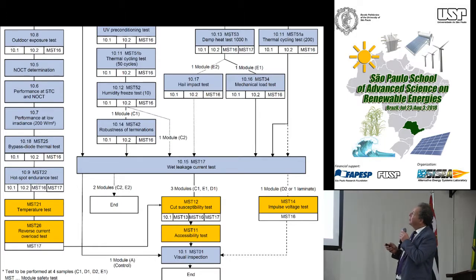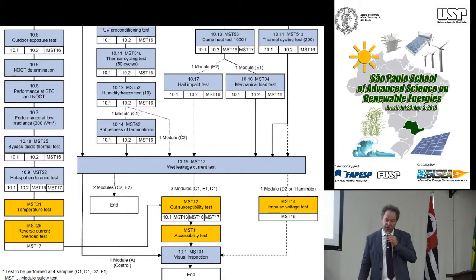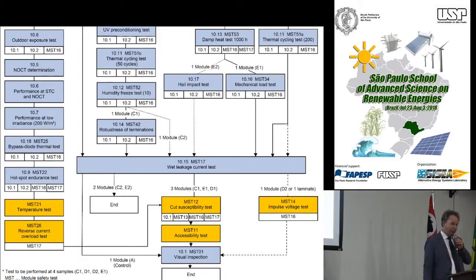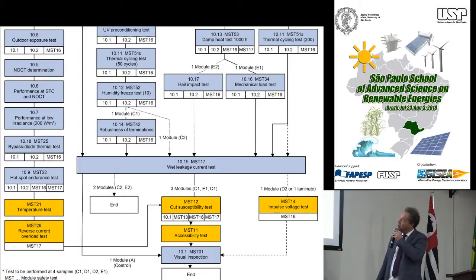Then again, we have the leakage test and the mechanical load test. This is equivalent to about 250 kilograms per square meter, or for a conventional module of 2 square meters, about 500 kilograms, and so on. So these are the tests the module has to perform in order to achieve the IEC 61215 certification. Another one is the thermocycling test, 200 times, and so on.